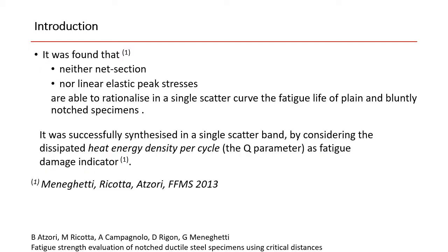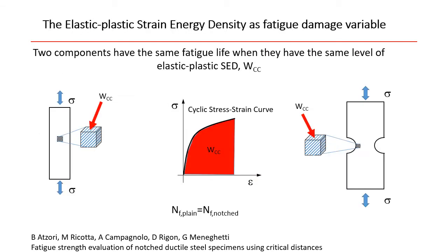We have found that neither net section nor linear elastic peak stresses are able to rationalize in a single scatter curve the fatigue life of plain and bluntly notched specimens. On the contrary, we have seen that the fatigue data can be rationalized in a single scatter band in terms of heat energy density per cycle as fatigue damage indicator.